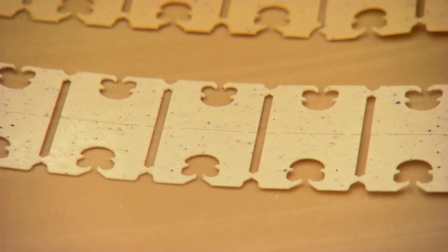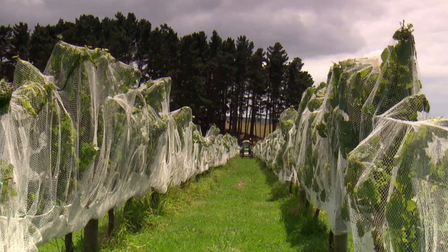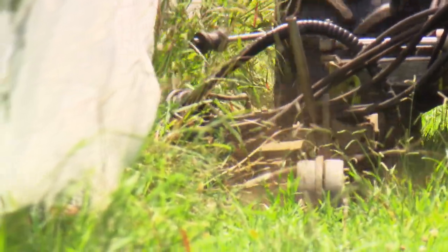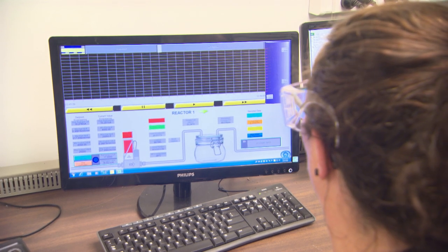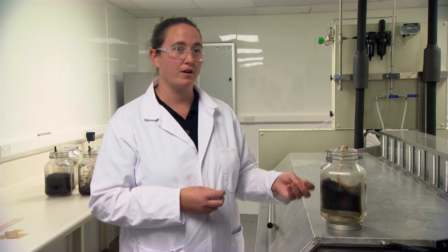With the clips we have designed, they can either be left on the ground and will biodegrade over a time period, or they can be collected up and put into compost. They may even be lawn-mowed into tiny little bits. Those options are all viable because they will eventually biodegrade or compost. What we've seen in the lab is that our vine clip degrades faster than PLA alone, and it degrades significantly faster than conventional polystyrene. The net clip we've developed will degrade in the environment within a few months to years.